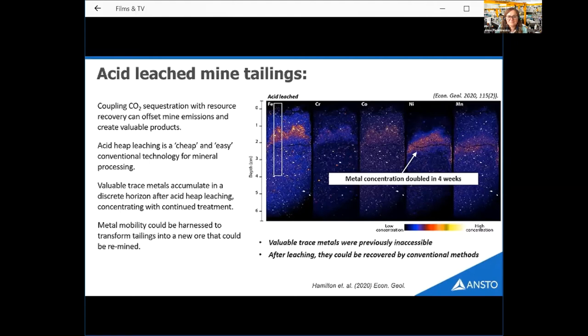So even though the goal of this experiment was to see just if we could produce that magnesium-rich leachates for carbon sequestration, the trace metals kind of stole the show, because we found that they accumulate and enrich in this discrete layer, getting more concentrated over time. So nickel doubled in concentration in 4 weeks in that zone. And you can see from this image how strongly it's been leached out of the upper section.